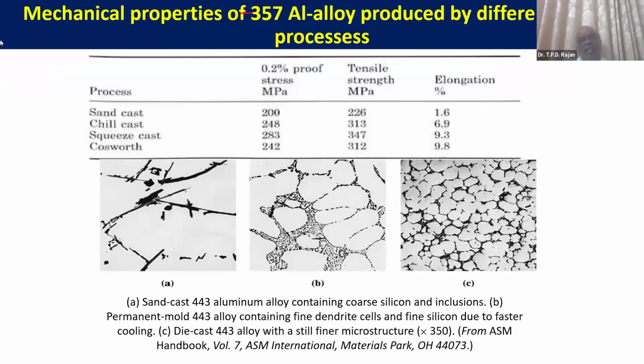But the advantage of squeeze casting is that once you apply the pressure, in a sand cast you have a very coarse structure, so it is refined slightly, but in the case of squeeze cast, you can see that it is almost completely refined because of the very fast cooling. So here we can see that the grain structure is getting refined. Because of that, a sand cast material having a typical tensile strength of 226 is increased to 347. That means there is an enormous increase in properties by going for a pressure die cast component.